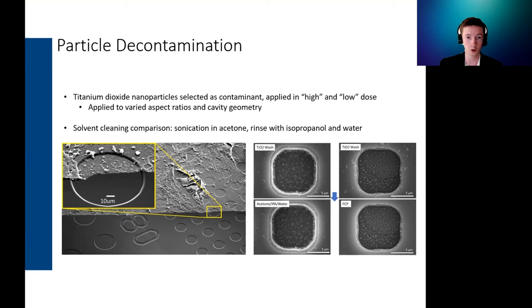You can apply it very regularly using a dilute solution, so it was the ideal choice for us. If you look at the two figures on the left side, you see the interface between a contaminated area and a non-contaminated area where the polymer was applied across the sample. The whiter area is where titanium dioxide is and the darker area is clean silicon, and you can see there's a pretty distinct difference there.